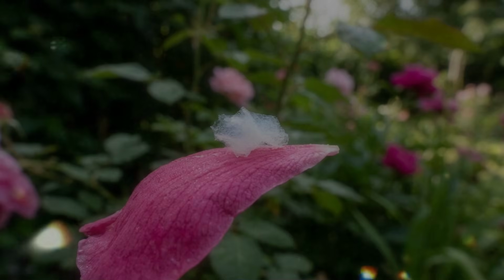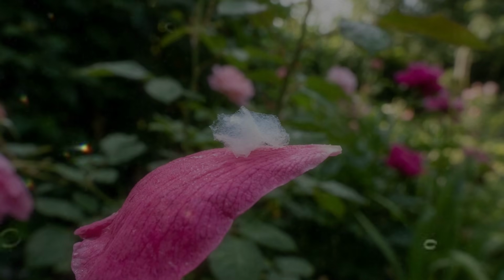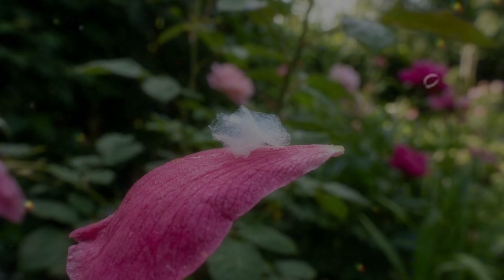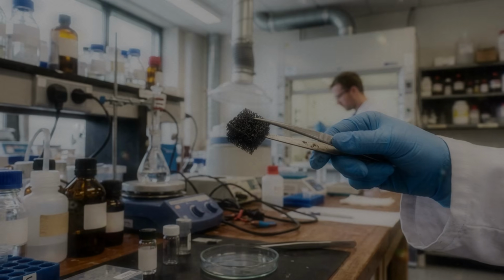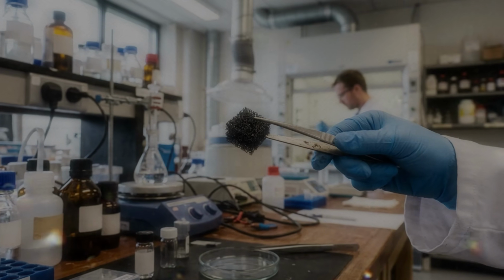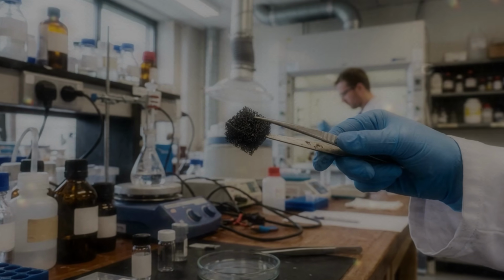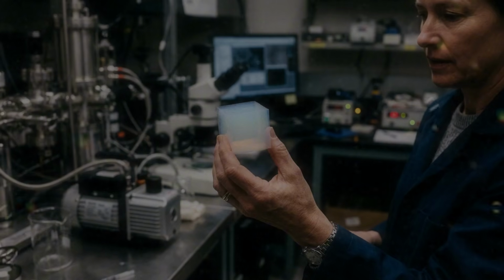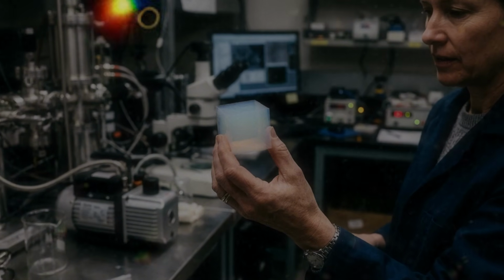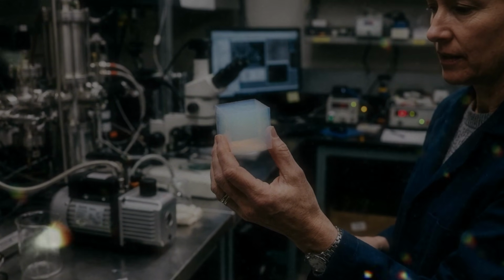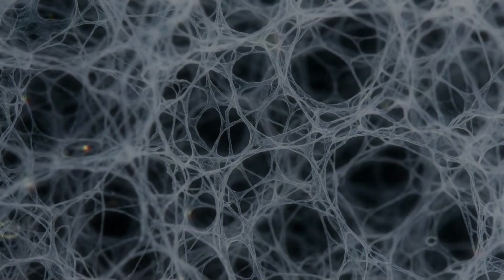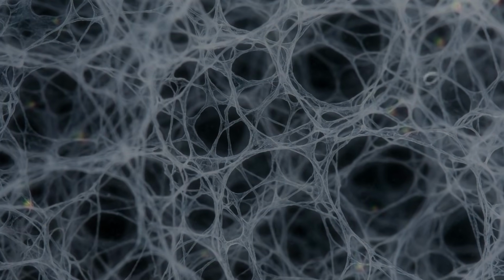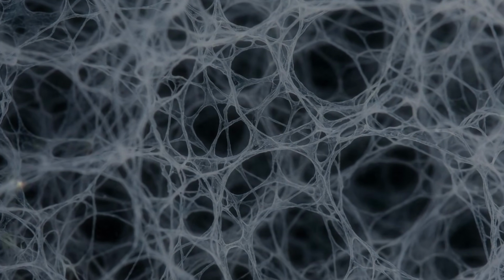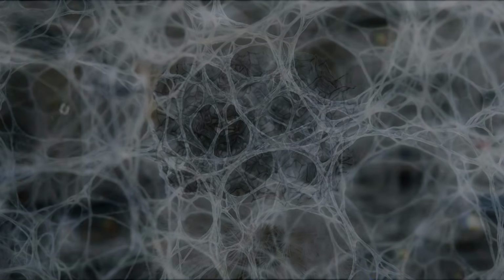Patience matters because rushing the exchange can create uneven conditions. The outside of the gel may change faster than the centre. Different parts may shrink at different rates. Stress can build until the sample cracks. Large pieces are particularly difficult because the distance from the centre to the surface is greater. A small laboratory sample might exchange its liquid relatively quickly, while a thick industrial panel requires much more careful control.